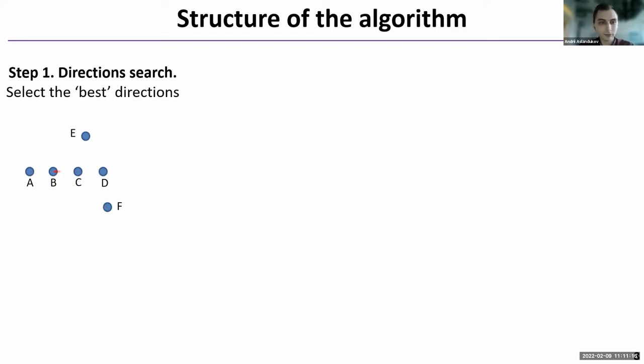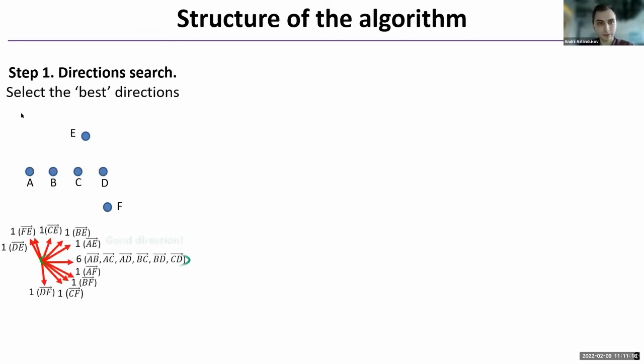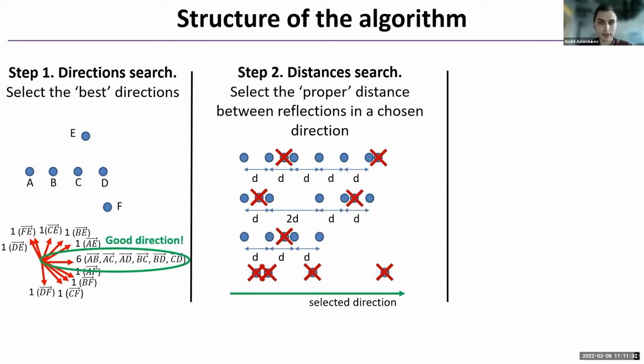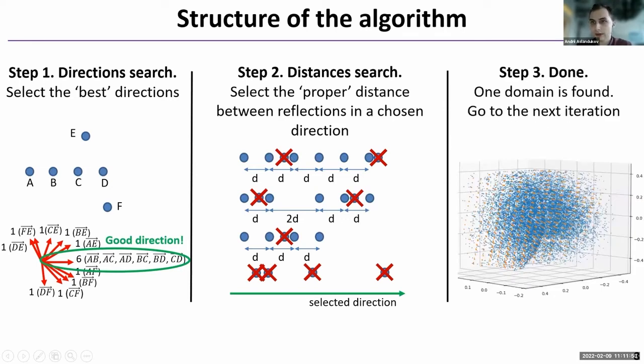For example, for given 6 points, we have 15 different vectors, but 6 of these vectors correspond to one direction. Then this is a good direction, which can be used in the second step. On the second step of the algorithm, we select the good rows of reflections, which boils down to selecting the proper distance between reflections in the chosen direction and kicking out wrong reflections. And after the second step, basically that's all. We found the reflection group belonging to the single crystal domain, and the program can go to the next iteration and remove the found group from consideration.